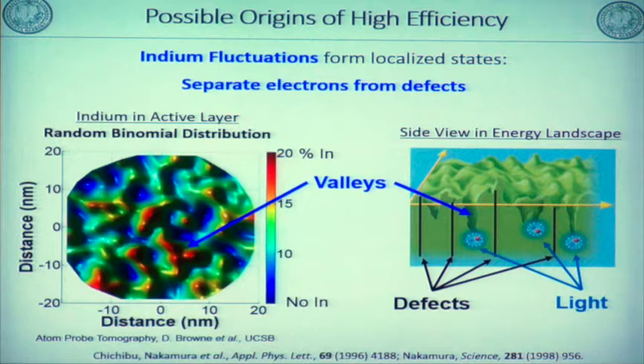Professor Chichibu of Tohoku University proposed localized states in '96. In indium gallium nitride there is alloy fluctuation, so there are some indium-rich regions and indium-poor regions. The indium-rich regions form the localized states. Injected carriers recombine radiatively at the localized states, which are caused by the indium-rich regions. So this is just an idea.